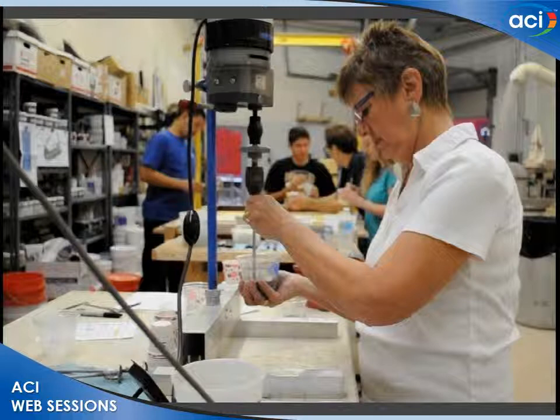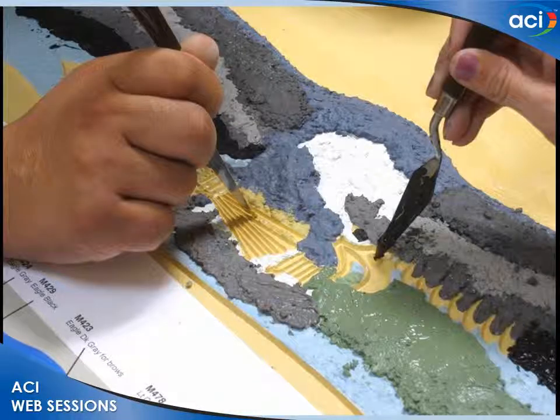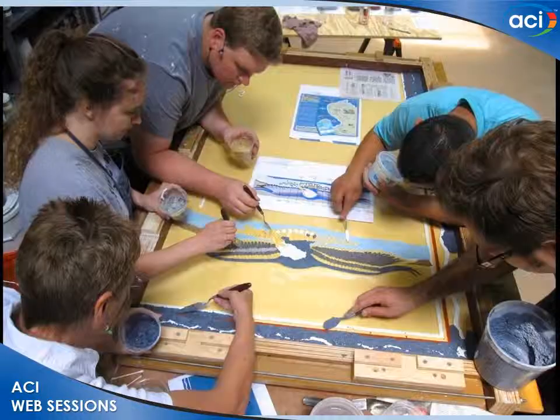For mixing, because we had such small mixes sometimes, it's about a half a cup mix. By the way, some of the glass aggregate was $45 a pound in the raw material, and we needed to crush that, and it would be $95 per pound by the time we were done processing and with all the waste. So we used a laboratory Hobart mixer that had enough torque and power to do that. But it still was a 20-minute mixing regimen just like you would do with a good concrete mix. We placed the material and consolidated it with artist palette knives into the little grooved areas. A tedious process, but it worked.